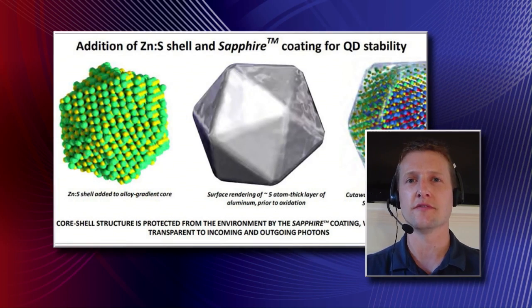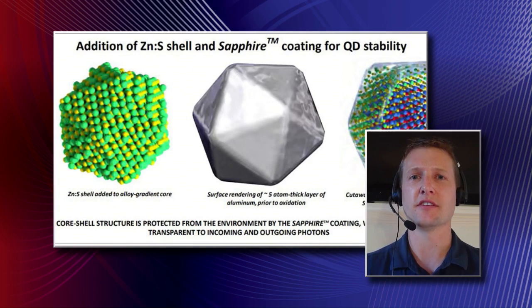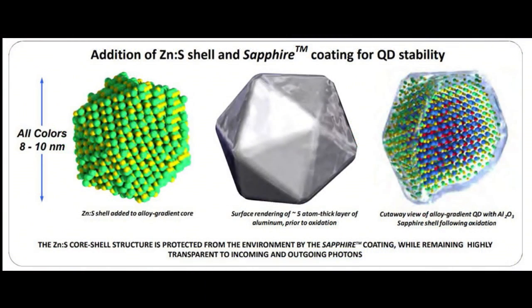Right. So this is one particular company's method to trying to create a quantum dot that's more robust, that will survive at higher temperatures for longer under higher light flux. And this is a technique that's being approached in different ways from various different companies. But the idea here in general is you take your quantum dot that's a normal core shell quantum dot. So this does not replace the initial shell that we discussed. This is in addition, to be clear. So this is already a core shell quantum dot. But in addition to that, they're adding here an aluminum oxide, which is also known as sapphire.